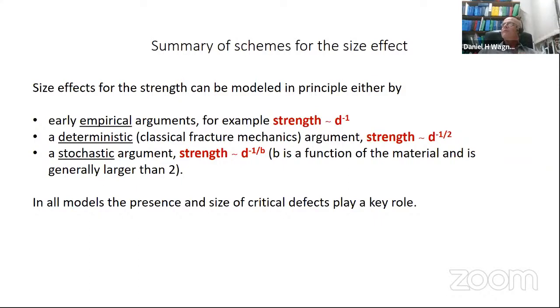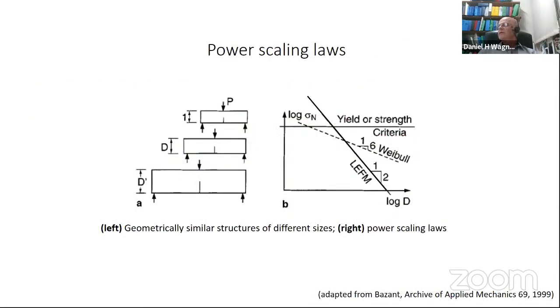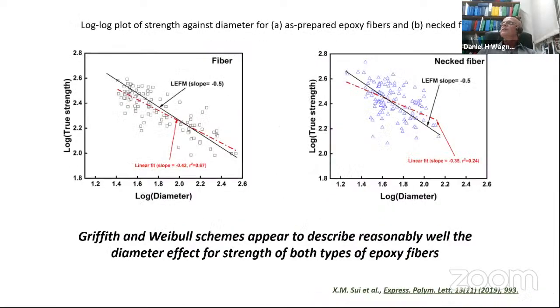I didn't mention that, but some people also derived the strength as being proportional to 1 over the diameter. It's deterministic. This is the classical fracture mechanics argument. And then there is the stochastic one, where b is a function of the material, generally larger than 2, where 2 is the fracture mechanics exponent, or 1/2. In all the models, the presence and the size of critical defects plays a role, of course, and we have these scaling laws here, as you can see, but that doesn't give us much novelty here.